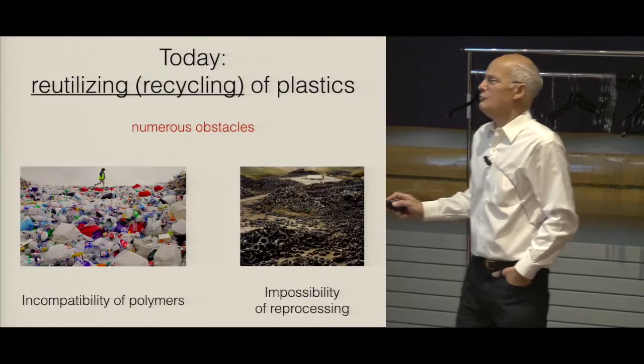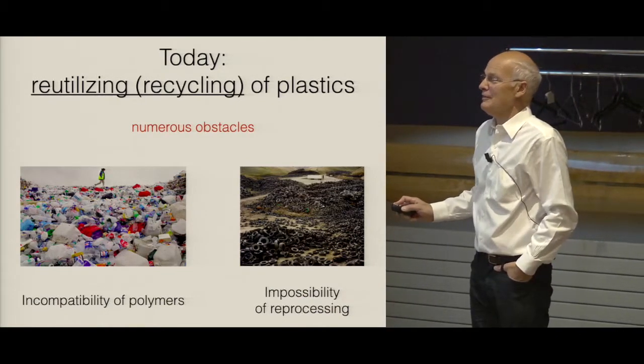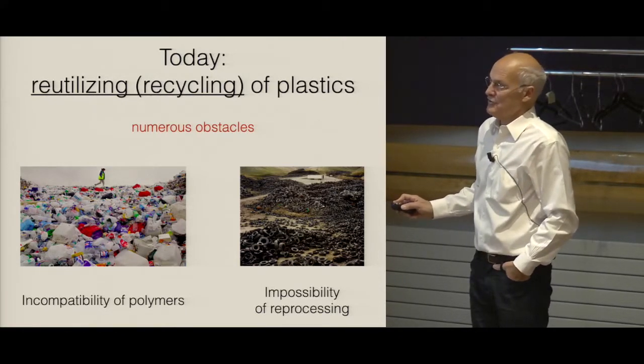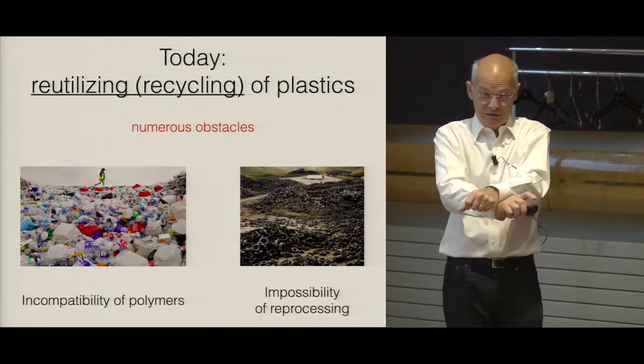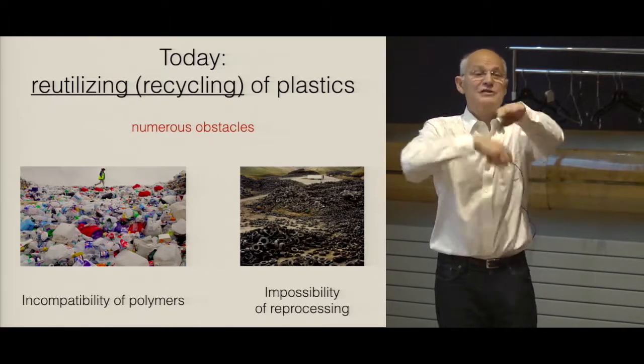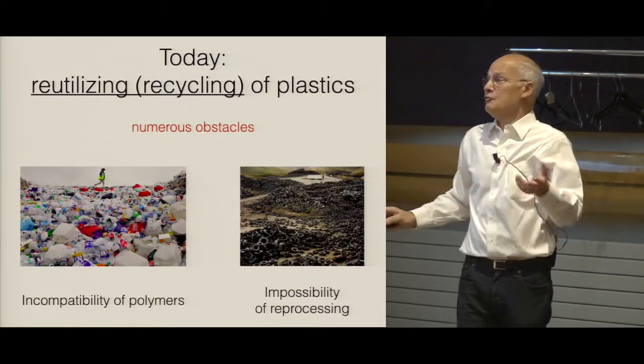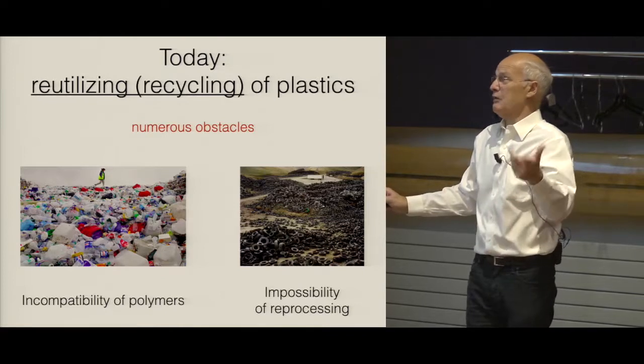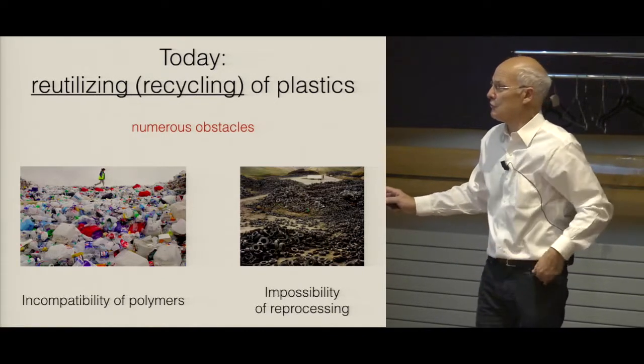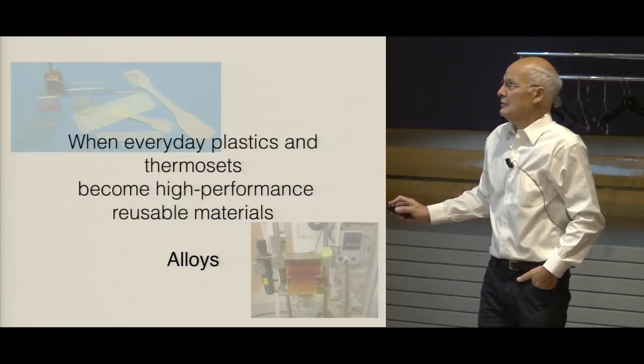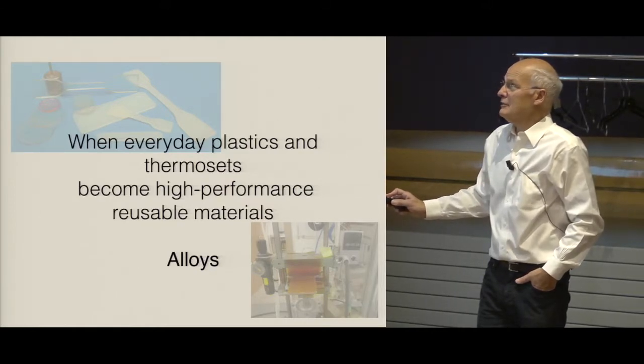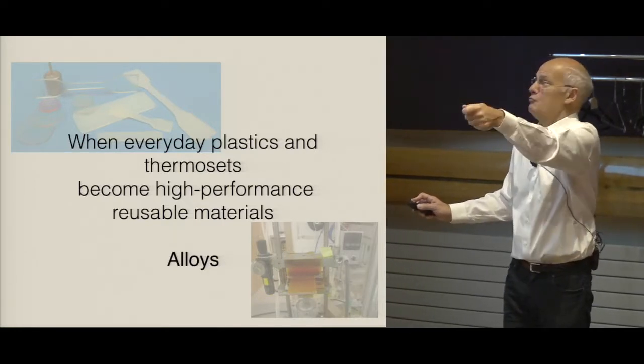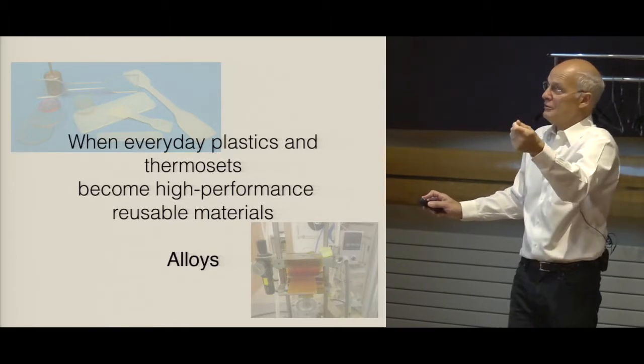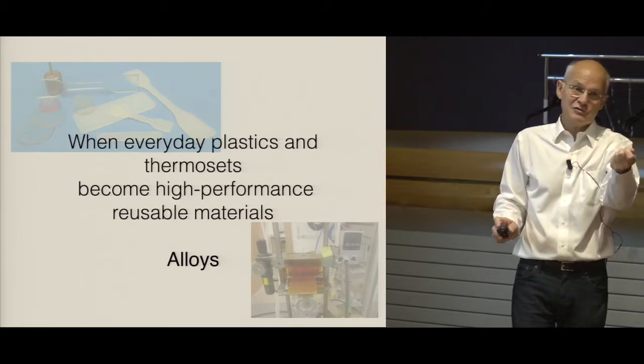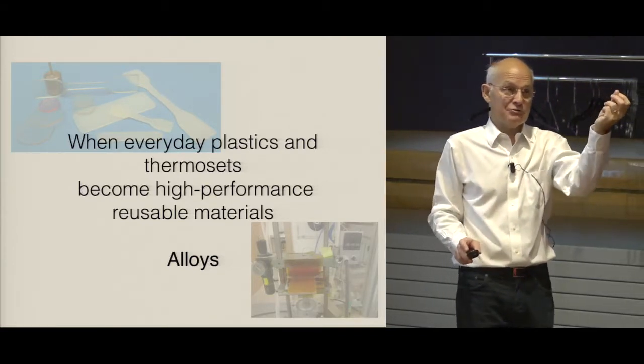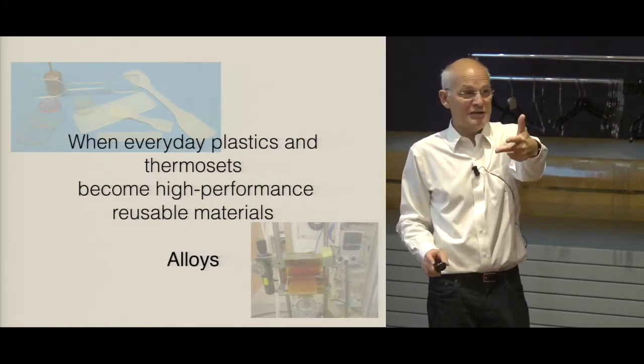So there are basically two problems. There are many problems with recycling of polymers and plastics, but one is that, as I said, long chains have very low entropy of mixing. So this means that I cannot take two polymers, mix them together, and make something of them. I have to sort them, because they are incompatible polymers. So this is one problem. And the second problem is that if it's cross-linked, we said it cannot be reprocessed. So the idea here could be that if we add these grafting groups into the system, then the polymers will be incompatible, but we can control the interfaces and adhesion between these polymers. So it could be that we could make a very high performance material by reusing plastics, with better properties. Okay.